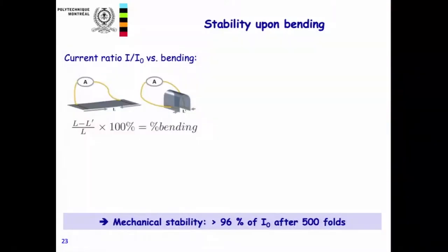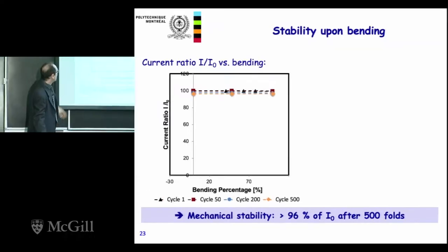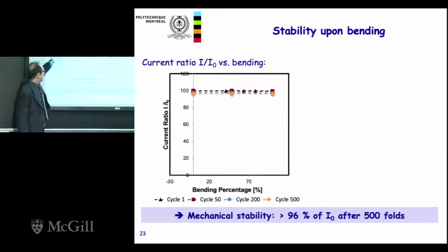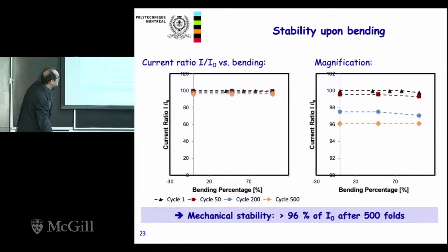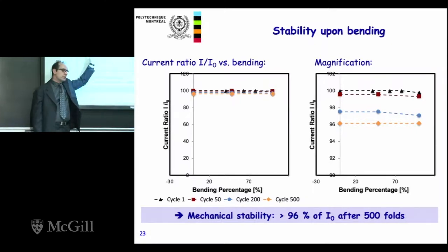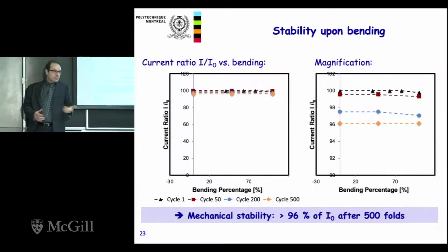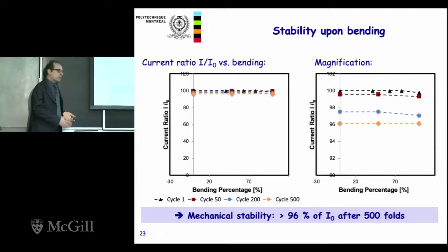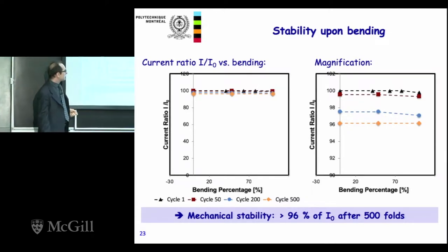Of course, then we made these flexible devices. Then sometimes you have people talk about flexible electronics just because they put materials on plastic, but actually we tested them. So we took our devices, we bended many times, about 500 times, and we looked at the change in current. This is after 500 bending. And actually, you see that the change in current is very low. It's about 4% with respect to the initial current. So actually, these materials are really flexible. They can be used in flexible electronics.